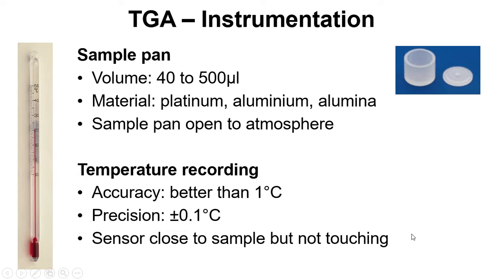One important reason is that if we have a metal thermocouple going inside our sample, that metal could catalyze reactions and catalyze the decomposition of our material. So it wouldn't be a true representation of the thermal decomposition. It wouldn't be a true experiment because we'd have the metal from the temperature sensor potentially catalyzing reactions.